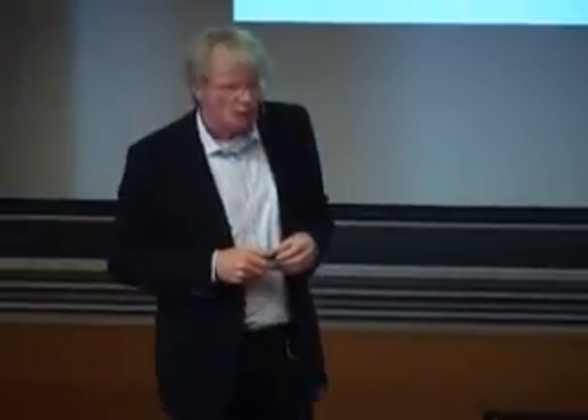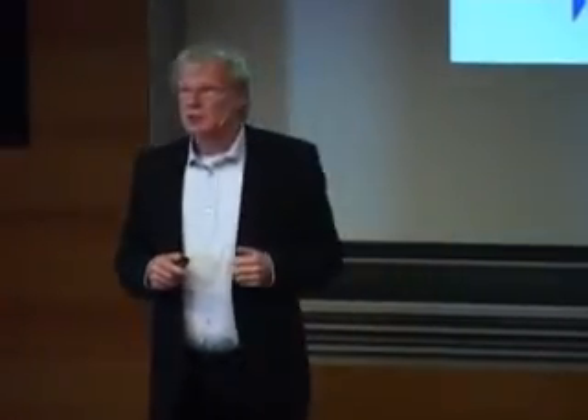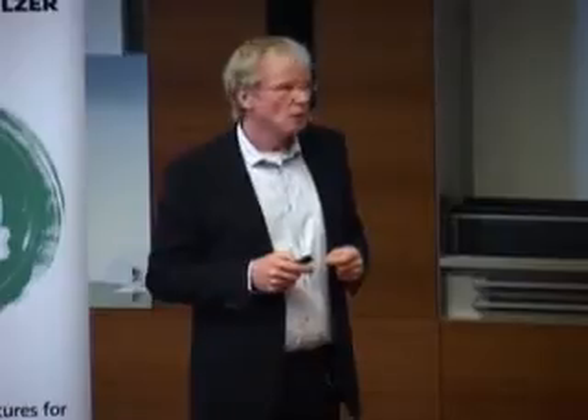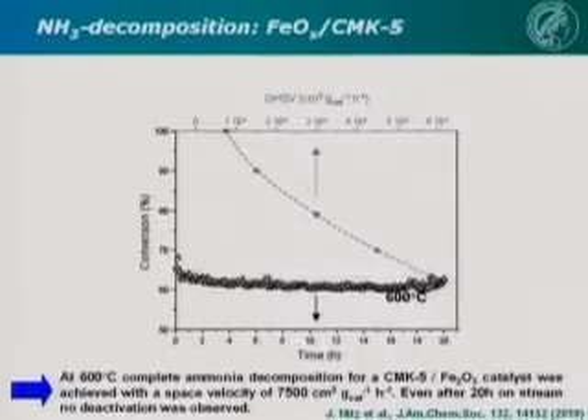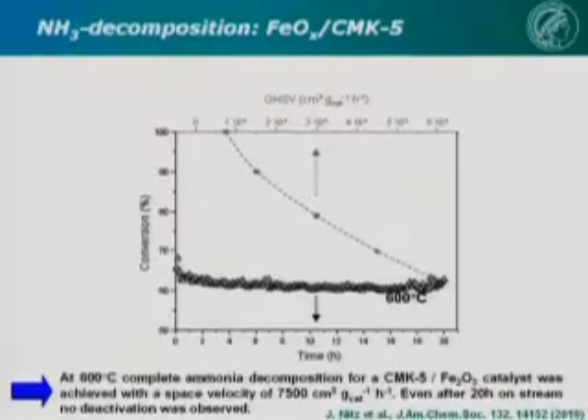And these catalysts were, at the time when we synthesized them, the most active iron oxide-based catalysts for ammonia decomposition which were known. Ruthenium is better with respect to activity, but ruthenium is way more expensive. So large processes you wouldn't base on ruthenium. And the catalyst is stable over at least 20 hours. This is the time we ran it. This shows you a nice example, I would say, for this nanoscale engineering, if we may call it like this.